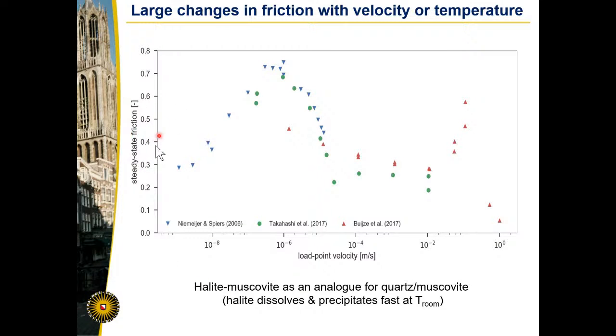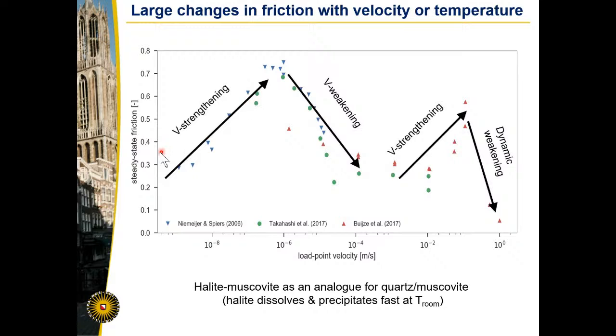So what's shown here is a bunch of different studies that have measured the steady state friction as a function of different load point velocities, basically crossing the entire range of velocities that you would expect in a natural fault. And you can see that there is, in fact, a velocity strengthening regime, a velocity weakening regime, and then another velocity strengthening regime, and then a dynamic weakening.